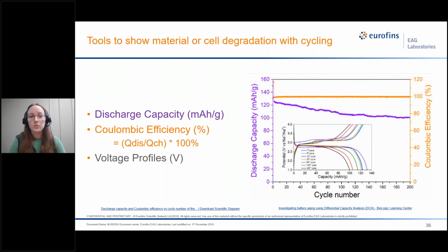So once we obtain the cycling data, we can actually analyze it in many ways, but here are some common routes such as the discharge capacity. So you can see in this plot, we can do a discharge capacity for cycle number, and we see it in the purple, and we would tend to see our capacity fade. We can also look into our Coulombic efficiency versus cycle number, and that would be our percentage ratio of charge delivered to our charge stored during charging, and that we can see with the orange. And now we would only start to see a decline if our electrodes are reducing their ability to store and release energy. We can also use our voltage profiles, so we can see our potential versus capacity plot. And this is also just another way to visualize capacity fade, either through our charging and our discharging cycles.